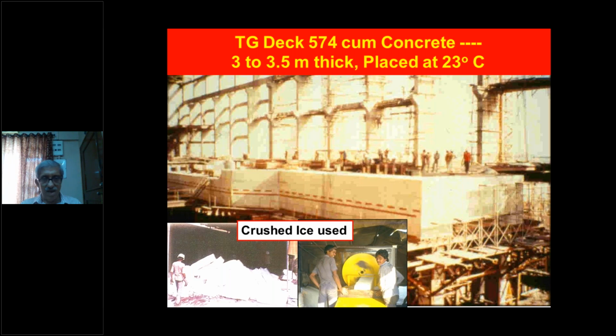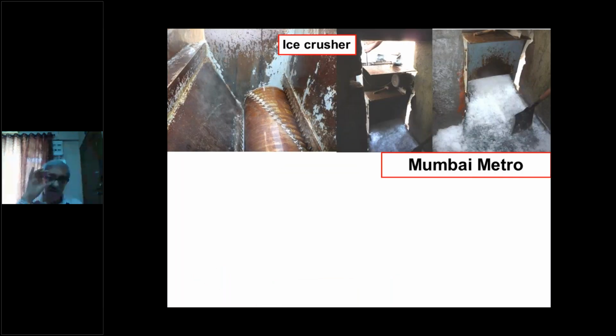You can see here crushed ice was being used. The Mumbai Metro also did a very good job and they had relatively slimmer sections of the beams, etc. But they had recommended 30 degrees centigrade for placing of concrete. So they had a contract with an ice manufacturer who gave them this ice crusher. This roller rolls and the spikes crush the ice. And the consistency of the crushed ice is just like crushed powder.